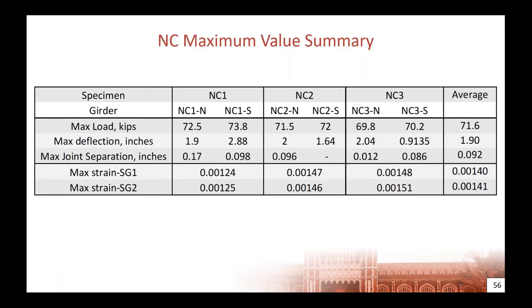In terms of maximum values for the new construction type joint, our ultimate loads were about 71 kips on average, about 2 inches of deflection, about 0.09 inches of joint opening, so over here on the right, and we didn't see strains high enough in our negative moment steel to represent yielding of the steel.